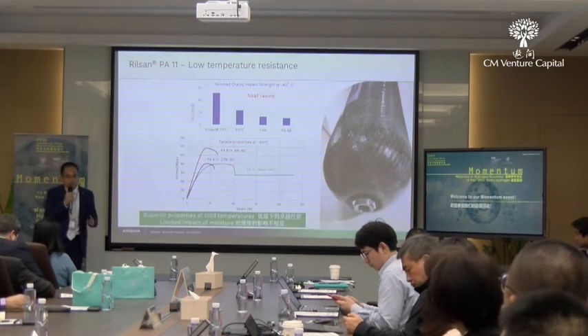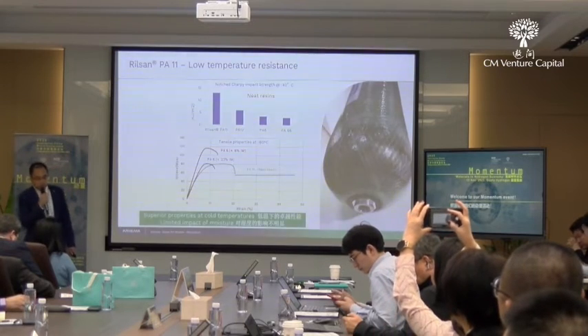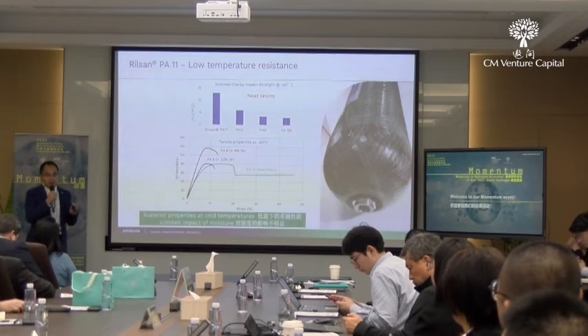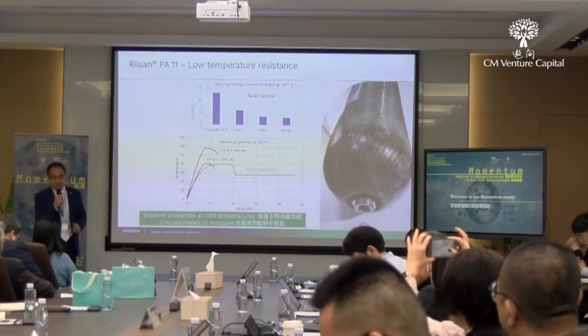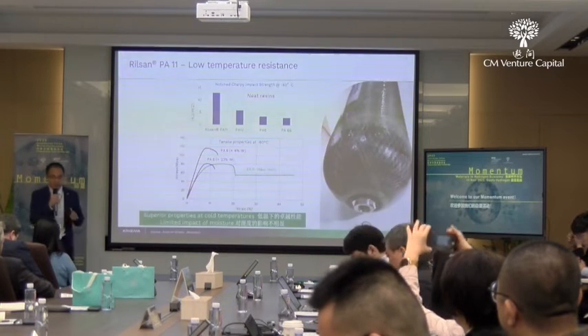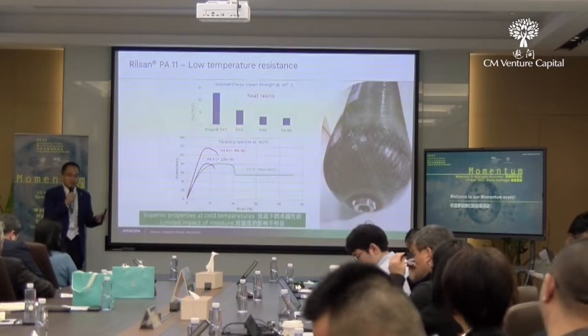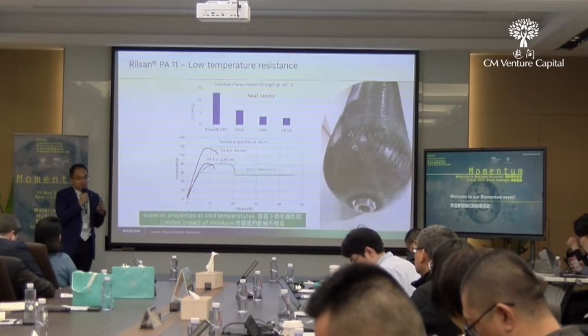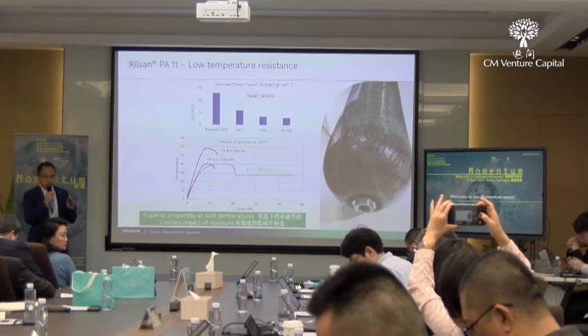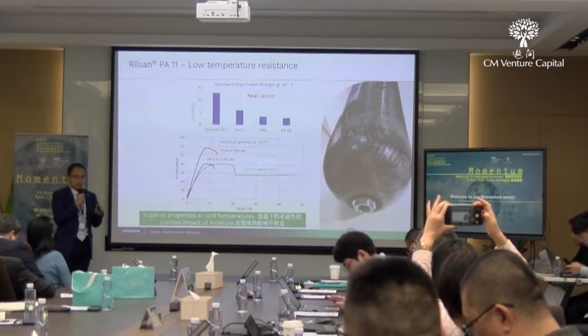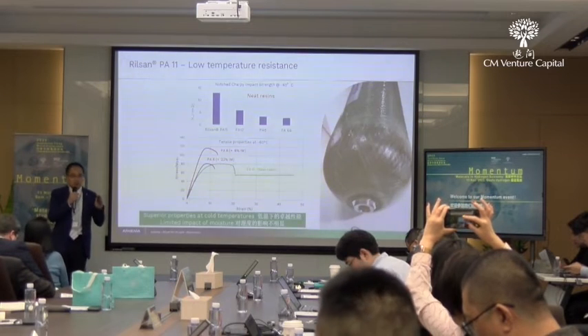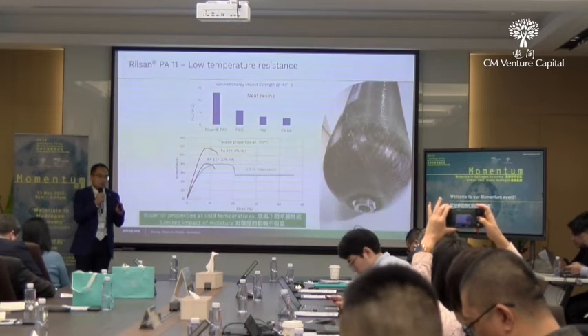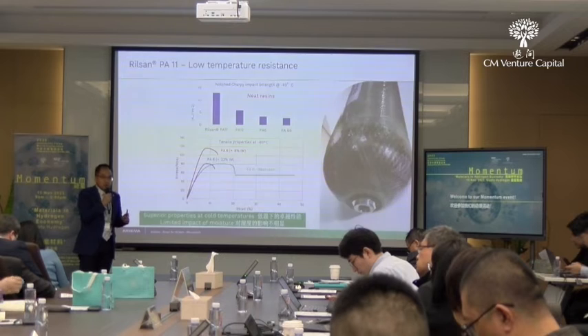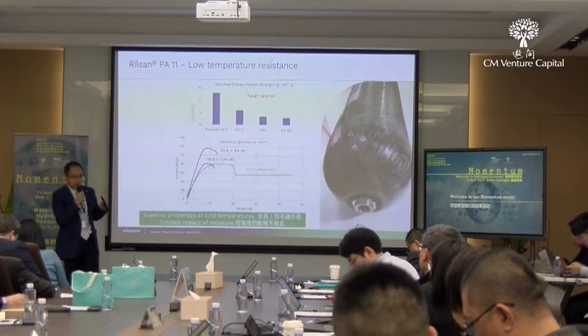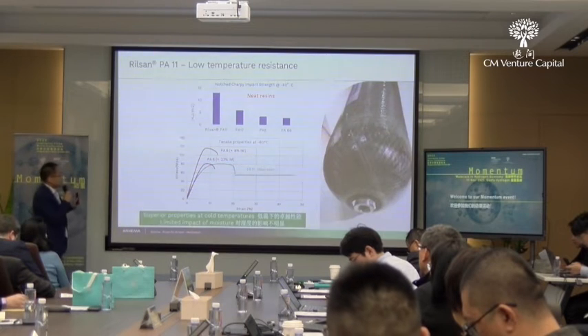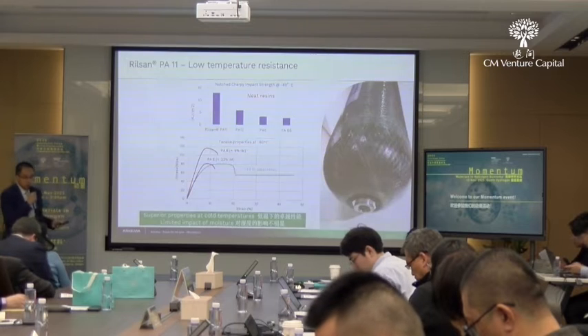Another key property for polyamide is for low temperatures. For hydrogen fuel cells, the key advantage compared with the battery is that they can work very well at low temperatures. You may see the battery will die at -40 or even lower, but for the fuel cells, the target is everywhere in the world. You may see some videos in Norway or in Switzerland, in the north of Europe, where the test temperature can go down to -60. So seeing the material properties at low temperature is very important to choose a good material.